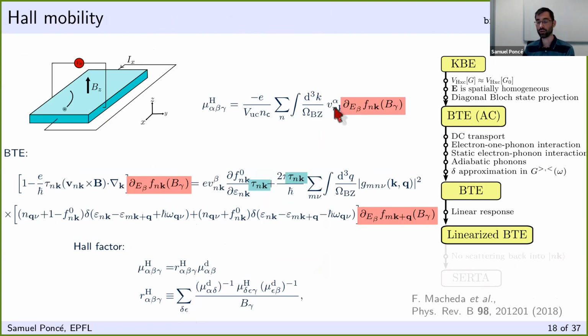Okay, let's say the electron velocity here, there are two ways to compute it. You can use a Wannier approach to express it, and this is what was used in the result that I have shown. But you can also use a dipole approach where you have the P over M, so the momentum, and then you have to take the commutator between the non-local potential and the local one. And so far, for a very long time, what was implemented for historical reasons in EPW, we were neglecting for simplicity this non-local part, and this is what we call the local velocity approximation.